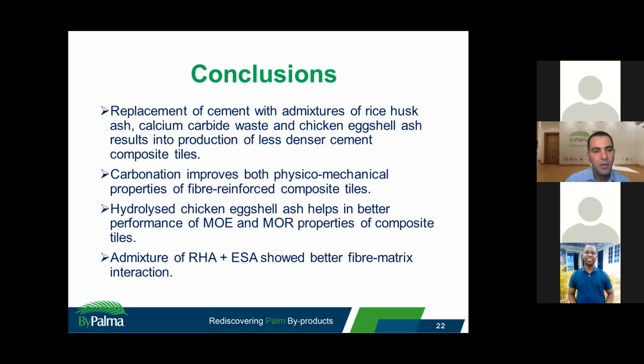Then we see from the result of the experiment that carbonation improves both the physico-mechanical properties of fibre-reinforced composite tiles, which I've explained in the earlier slide. Then hydrolysed chicken eggshell, which I explained, the conversion of eggshell from calcium carbonate to calcium oxide to calcium hydroxide, helps in better performance of Modulus of Elasticity and Modulus of Rupture of the composite tiles.